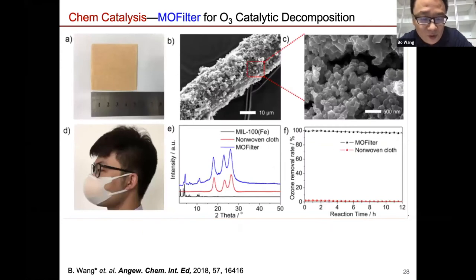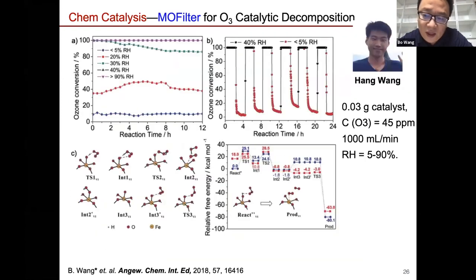And of course, using our simple hot pressing method, you can grow MOF on different substrates, in this case non-woven fabric. You can directly make a mask out of it for PM2.5 capture. And in this case, it's ozone decomposition. Under very high airflow velocity, you can decompose your ozone very nicely.